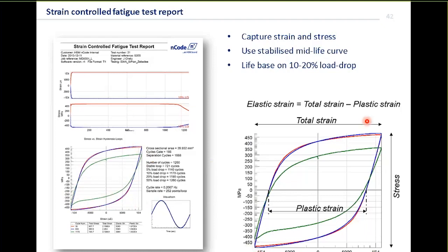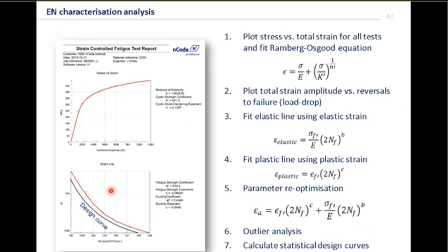These are the stabilized loops. And what we're interested in here is what was the elastic strain and what was the plastic strain. So the total strain is the distance from left to right here. From this loop, we can see where it crosses the zero stress line, then that becomes the plastic strain. And if we take one from the other, that gives us the elastic strain. And we use those two values, elastic strain and plastic strain, when we fit the Coffin-Manson equation down here. So when we characterize it, this is what we do. We start off first of all by characterizing the Ramberg-Osgood, the cyclic stress strain plot that you can see here.